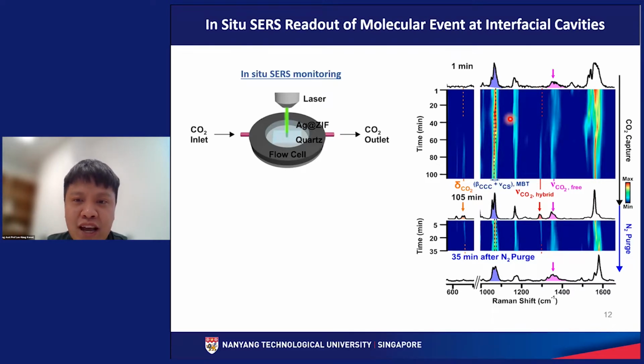Okay. So the redder it is means that the intensity of this peak is higher. So if I have a blue region, it simply means that there is no peak over there. Okay. So at the end of our CO2 absorption at around 105 minutes, we can see that this initially broad peak over here will get more narrow. So there is an evolution of a new SERS peak over here at around 1,280. Over here in the 660 region, we can see that there is evolution of another peak at around 660